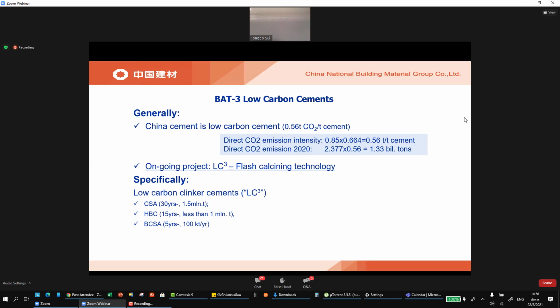And the third one, best available technologies, is the low carbon cement. Generally, we can consider Chinese cement as a low carbon cement because, when we made a very simple calculation, we can see that the direct CO2 emission intensity of Chinese cement is something around 0.56 tons CO2 per ton of Chinese cement. Accordingly, we can calculate quickly the direct CO2 emission last year for the Chinese cement industry. That's something around 1.3 billion metric tons.